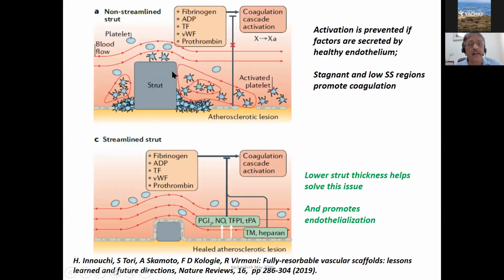The lack of endothelialization is caused by the thickness of the strut. So compared to metal struts, these cobalt chromium struts, for example, are about 80 to 90 microns. But the biodegradable stent strut is about 150 to 200 microns. Because it's made out of polymers that are lower in mechanical properties compared to metals, they have to be thicker to withstand the pressures inside the arteries.